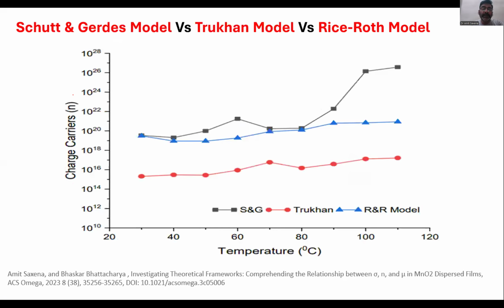So this is the graph which we received in our recent publication in ACS Omega. You can see that all three models are offering different values. But interestingly, you can see that the concentration of charge carriers increases directly just after, or just near, the melting temperature, because the structure is PEO based. The PEO is offering the melting close to 60 to 70 degrees Celsius. You can see that near the melting temperature, the concentration of the charge carriers increases.